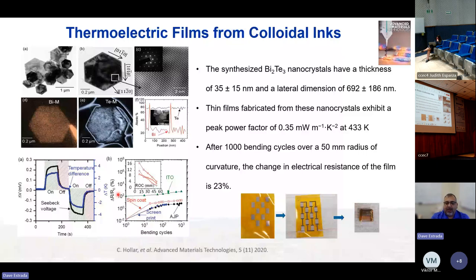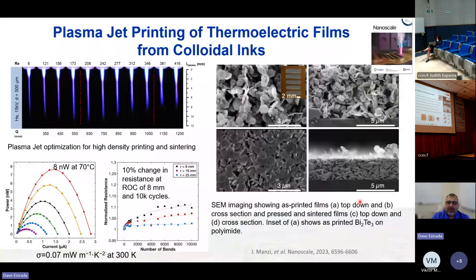Where we're moving now is to increase power density for these devices, and we're doing that through this folded origami approach, where we can connect these thermoelectric legs in series and then fold them up to get a higher power density. We showed that we could do that with spin coating and aerosol jet printing, but the same ink could be used in plasma jet printing as well. And so working with Harish Subbaraman, who's now at Oregon State University, we showed that we can control the plasma characteristics through the gas flows and the voltage applied to generate the plasma.